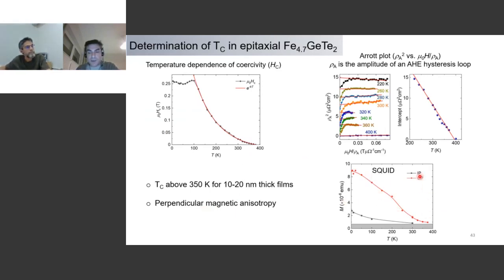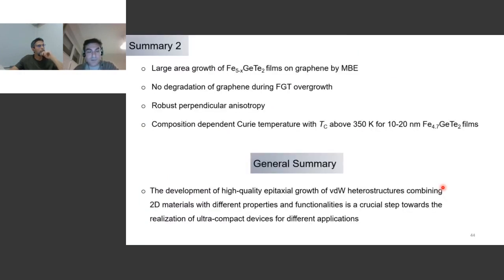And this is done by SQUID, in that you apply an out of plane magnetic field, and then you probe the magnetization. So this is quite promising for future applications of these 2D materials in spintronic devices, and it's large area, so it's a patternable form of material. So in that case, I can say that we could advance beyond the state of the art, which is, as I said, flakes exfoliated from bulk crystals. So with that, I summarized this part, and so that we could achieve this large area growth.